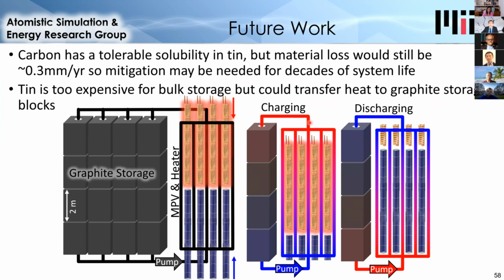And one way to mitigate this is actually automatically implemented by the system shown here. So if we look at the charging case, the hot zone is at the top and the cold is at the bottom. So during charging, we could have material loss from the top and deposition in the bottom. But then during discharging, we would have deposition in the top and material loss from the bottom. And so this might serve to reverse the material loss, and this could cause the system to survive longer or have a lower loss rate than this predicted 0.3 millimeters per year. And so this is one alternative version of this TAGS technology that could be taken forward.